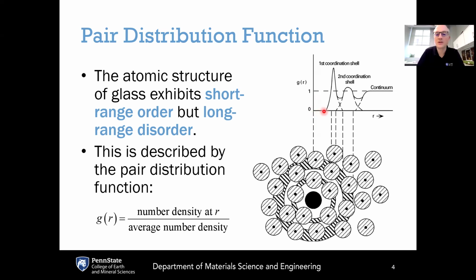And when we have that first nearest neighbor, that's where we see the first peak. That first nearest neighbor peak corresponds to this inner circle shown here. So I'm highlighting this with my laser pointer, and you can see that all of these first nearest neighbors, that means the atoms that are closest to the central atom, are all located at roughly the same distance from that central atom. And this is what we mean by short-range order. The short-range order is telling us that there is a preferred bond distance between any given atom and its first nearest neighbor.